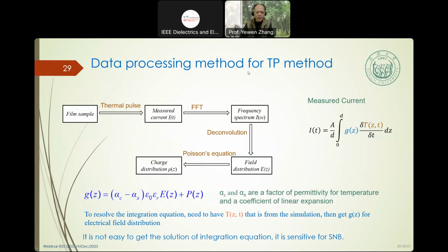So this is a data processing method for the TP. The sample is excited using the thermal pulse, and we measure the current. We use FFT to get the frequency spectrum. Then after deconvolution, we get the field distribution. By Poisson's equation, we get the charge distribution. You can find that this equation is very similar to the PWP. The displacement P changes with the temperature T. But the temperature is not a wave. The temperature is something like diffusion, not a propagation. So it's not easy to resolve this integration equation.